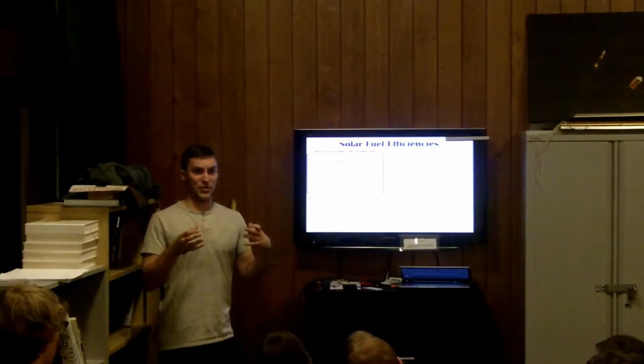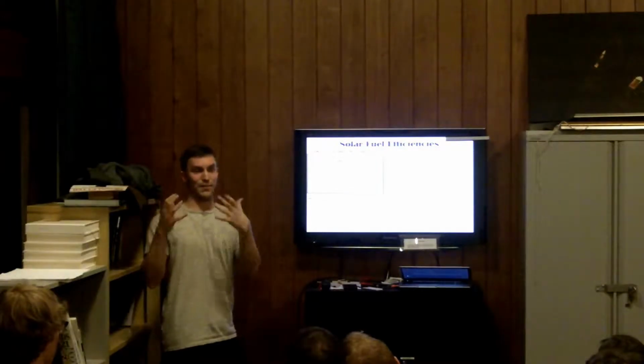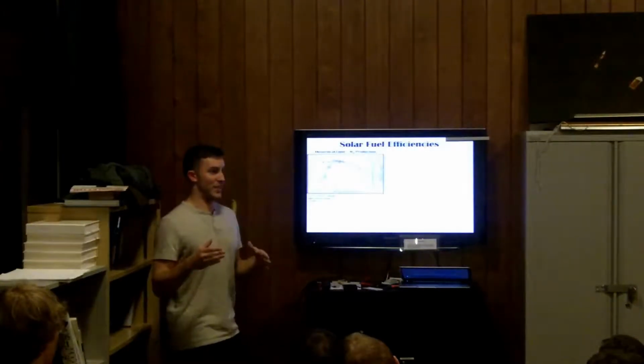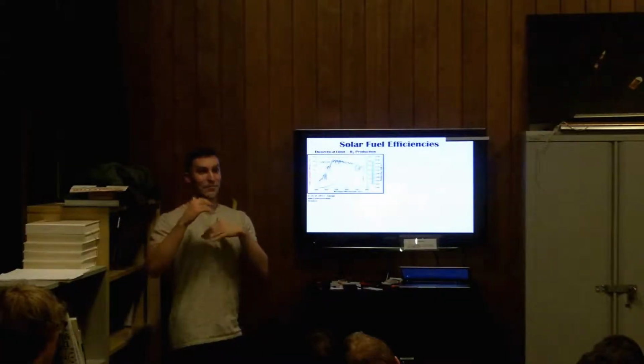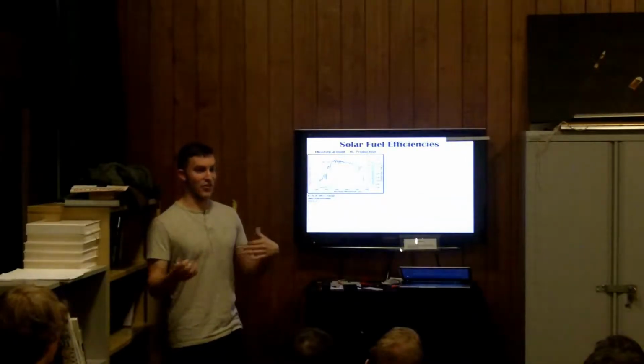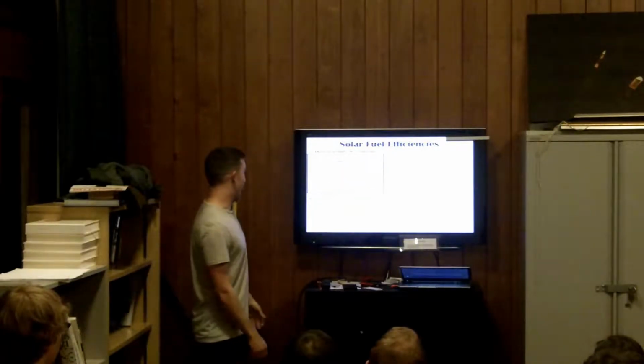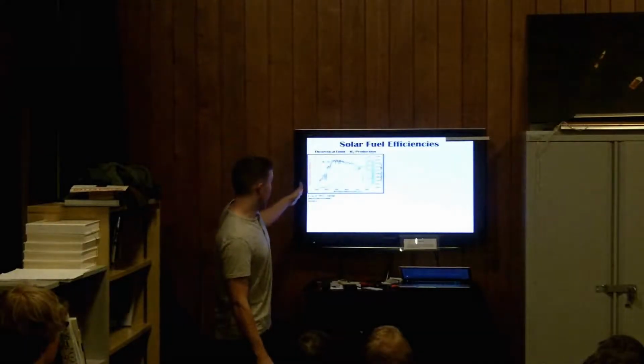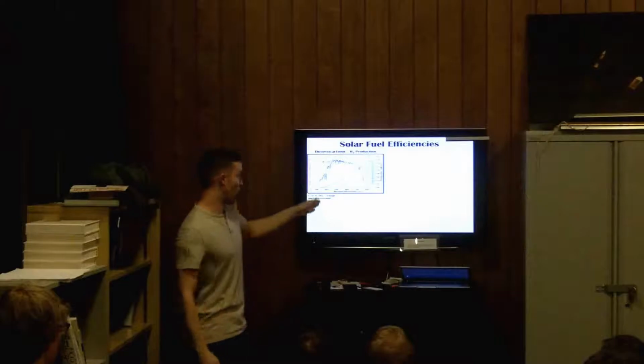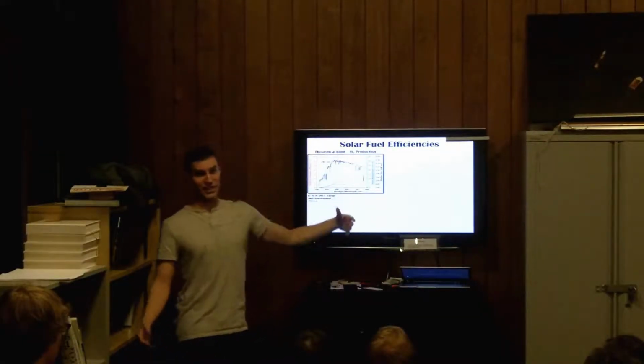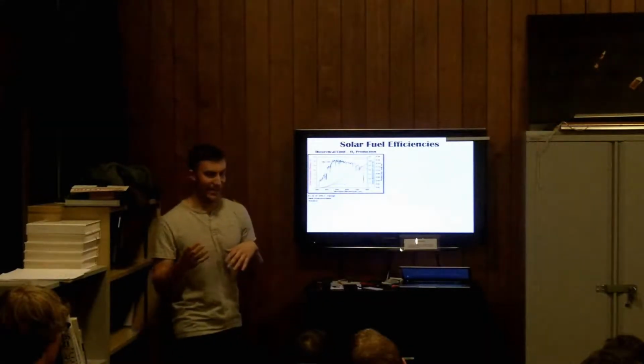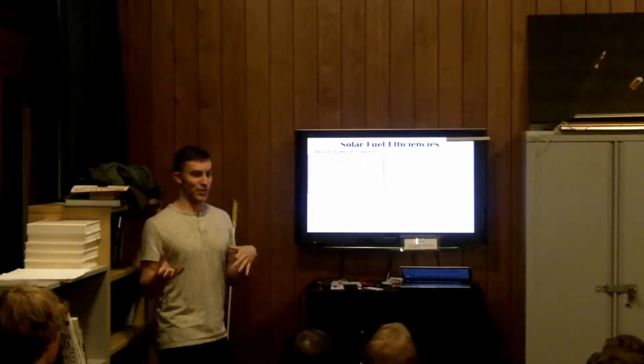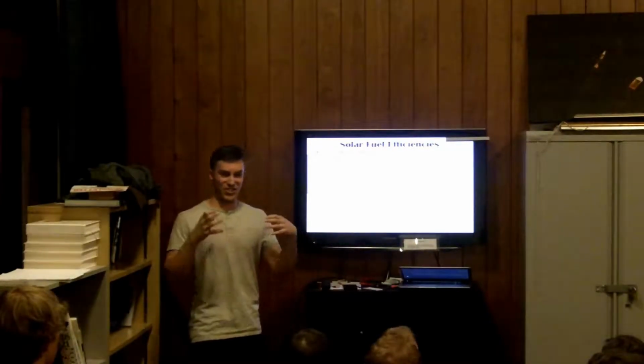And so for our materials, there's a certain wavelength beyond which the photons don't have enough energy to excite that electron transfer through our material. So you need to take a comparison of the solar spectrum and the band gap of your material to see how much of the solar spectrum you're actually using and capturing to make these solar fuels. And the red trace here is showing you that as the band gap of your material moves to a lower energy or a longer wavelength, you're able to theoretically achieve a higher efficiency with the material. So we want to narrow that band gap as much as we can, but we have to stay above that 1.23 volt boundary that I referred to before, because of a certain amount of energy that we have to have in order to induce the water splitting reaction.